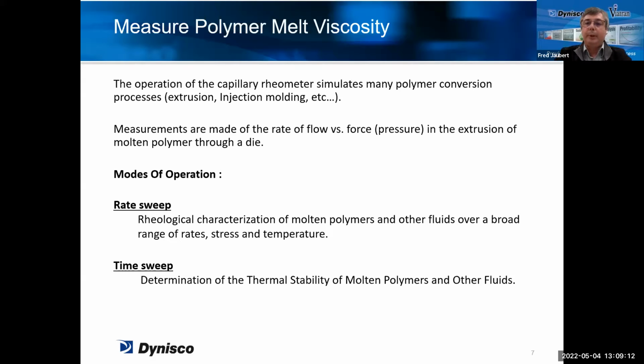You have two modes of operations to run the capillary rheometers. One is called the rate sweep. Basically, what you are going to do is that you are going to vary the speed of the motor. So you are going to vary the shear rate, and then you are going to measure the range of shear stress and viscosity over the range of shear rates. And the second possibility with this instrument is, instead of running with various shear rates, you can run the same shear rate over a period of time, and you can also do pauses in between, and then you will be able to measure what is called the thermal stability of a polymer.